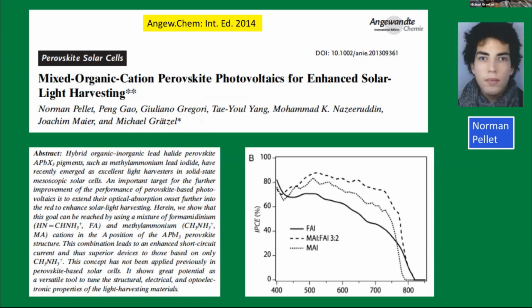And so then with this group, again, Norman Pellet was first, he discovered, I think he was jointly appointed by Stuttgart and our lab. And so we found that we could stabilize the lead formamidinium by just adding a little bit of methyl ammonium, say 10%. And so you see what we say there. This concept has not been applied previously in perovskite-based solar cells. It shows great potential as a versatile tool to tune the structural, electrical, and optoelectronic properties. And this statement has been verified by the last year's development, so it was a correct prediction.